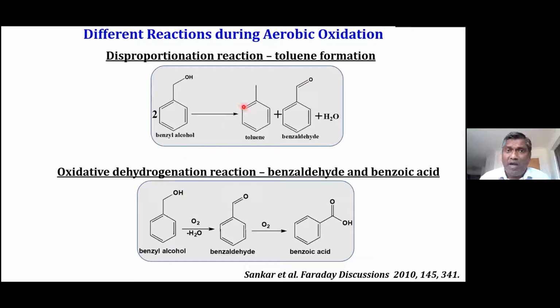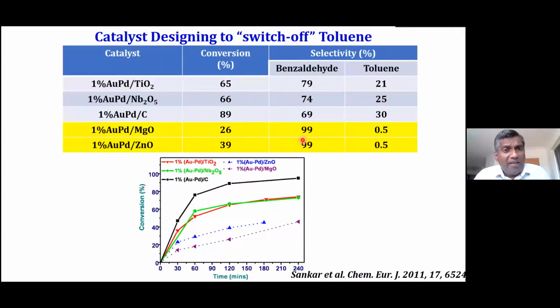Now, if we don't want toluene, we should somehow suppress this disproportionation reaction. I will come back to the logic behind choosing different supports in the next couple of slides, but we prepared different gold palladium catalysts with different supports. For example, titanium oxide, niobium oxide, carbon, magnesium oxide, and zinc oxide. If you look at the first three catalysts, approximately 25 to 30% toluene is formed. For the last two catalysts, we have almost switched off toluene production. However, the conversion is much less.